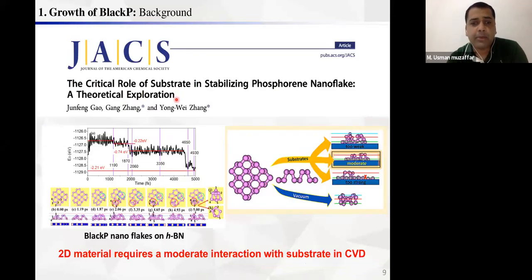Here is another attempt made by Professor Yongwei Zhang from Singapore University, a well-known professor in the growth field. They considered a number of substrates to grow black phosphorene on. Unfortunately, he also didn't find a physically realistic material as a substrate. He ended this project with the conclusion that if the interlayer coupling between the substrate and a monolayer is in the too weak regime or too strong regime, both are not good for stabilizing the monolayer.